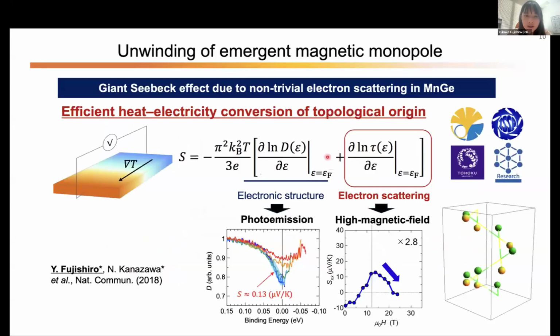And very interestingly, we discovered that this pair annihilation might enhance the efficient heat and electricity conversion, where we observed a very gigantic magneto-Seebeck effect in this manganese germanium.